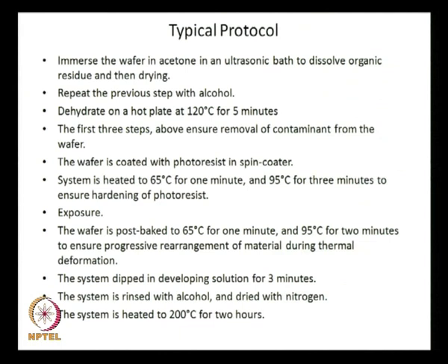The system is rinsed with alcohol and dried with nitrogen. The system is heated to 200 degree centigrade for 2 hours. Again this process, this 200 degree centigrade for 2 hours, you ensure that all the rearrangements are done, completed, frozen.